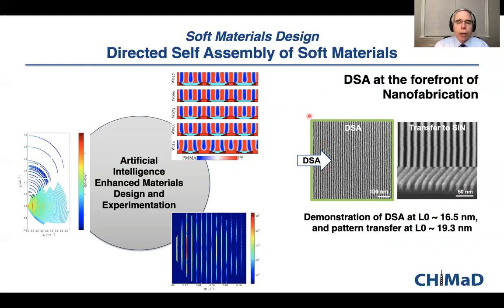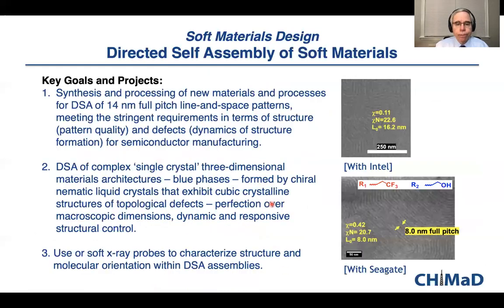And they're doing this by using a combination of simulation that is informed by experiments using artificial intelligence optimization processes that allows you to model the phase separation process to give you the block, to give you the phase separation necessary to give you the lines, but it's informed and tested by experiments. And so the X-ray metrology is an important part of this effort too.